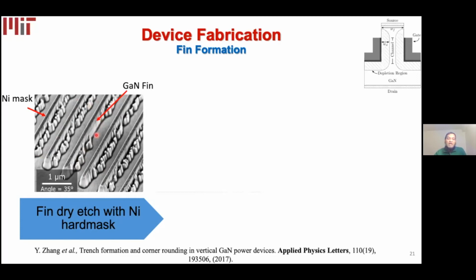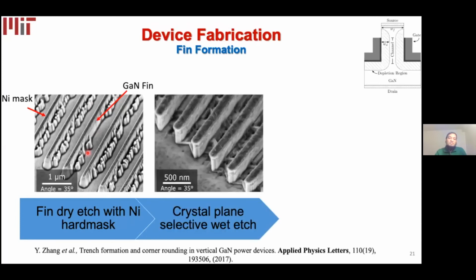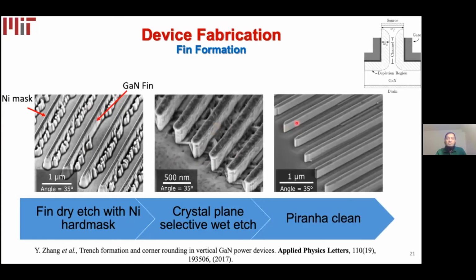Since we want to have our channels across the sidewalls, it's very important to get rid of these damages and get a very smooth sidewall for our subsequent ALD deposition and gate metal patterning. So to do that, we align our fins with a specific crystal orientation that helps us to use a crystal plane selective wet etch, and that only etches the sidewalls significantly and has a very low etch rate in the other crystal planes. And after a successful crystal plane selective wet etch and cleaning of the substrate, we get very nice smooth fins with these very excellent sidewalls.